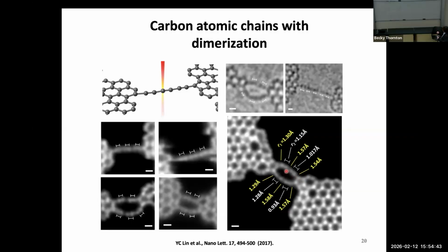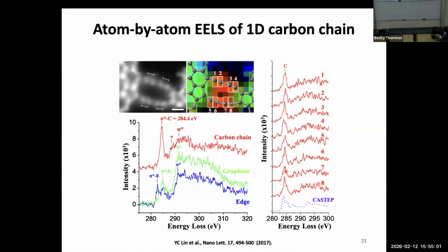As you can see, this is a kind of Peierls distortion. If you have a one-dimensional structure, the carbon atoms cannot be at the same distance. They have some dimerization. In this case, as you can see clearly, these two carbon atoms are dimerized. And of course you can make spectroscopy at 30 keV. If you make spectroscopy from all of these places, the green one is a normal sp2 carbon, and the red and blue ones are the edge carbon atoms. So you have different places. The carbon K edge shows another peak. And if you have the carbon chains, again, the pi star peak just shifts a bit. But as you can see, we can get the spectrum from each carbon atom.